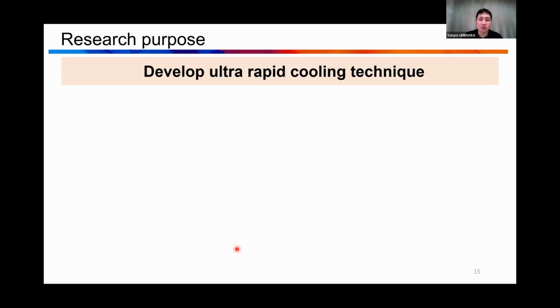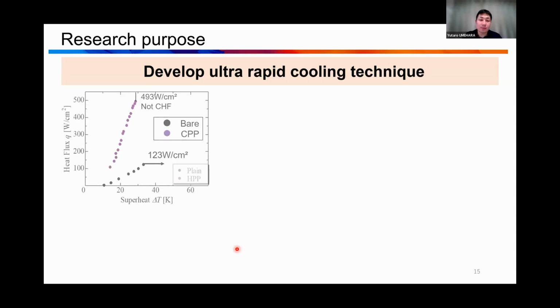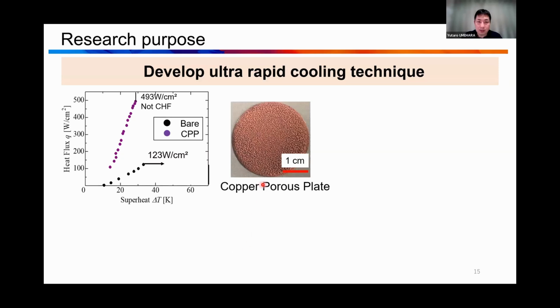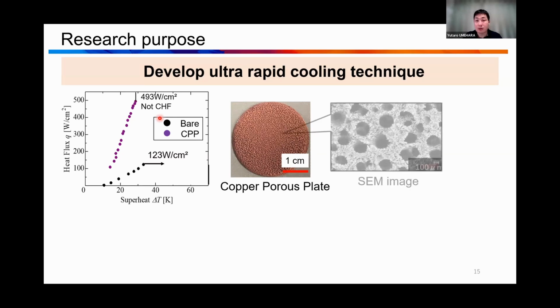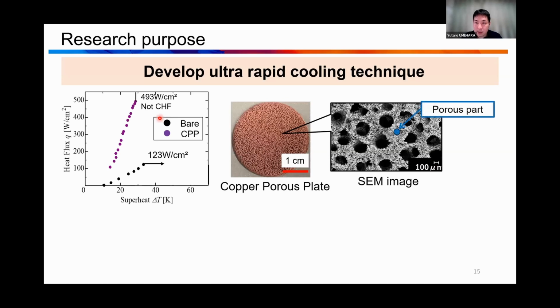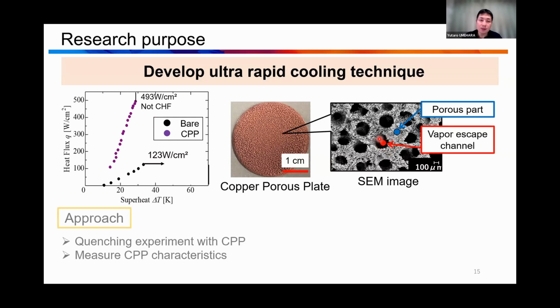But our research proposal is to develop an ultra rapid cooling technique by using a copper porous plate. So this one is a copper porous plate, and this copper porous plate can enhance the critical heat flux. They also tried to use it to improve the cooling phenomena. This is the same image. This part is the porous part, and it also has big pores in the surface. So we try to use this to enhance the cooling characteristics.